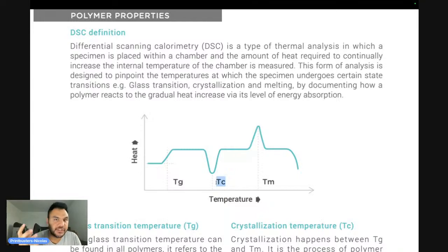But if you give too much energy, then they are going to try to form the crystal, but they still want to move. There's too much energy, and then the crystal deforms, right? So it forms and then deforms. And the higher you increase the temperature, the crystal cannot even be created. And the TC is the sweet spot: the polymer has enough energy to very quickly form the crystals, but not enough energy to break the crystal. So TC is the ideal temperature for crystallization.